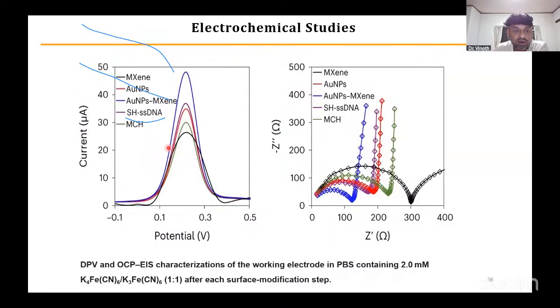These are the electrochemical studies. Here we can see that the gold nanoparticle combined with MXene shows the highest peak current when compared to pristine gold nanoparticles and gold on MXenes, and the thiolated DNA. These are the impedimetric analysis studies, which directly depend on these different materials.